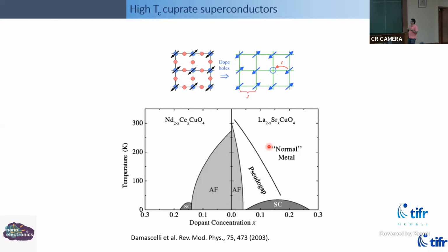It has variations from one family to another, but there are some common features: you have this superconductor, then you have an antiferromagnet, which is very close to it. And you can get a huge amount of variation in superconducting transition temperature by changing the chemistry of these compounds. And that's the main material that we use.